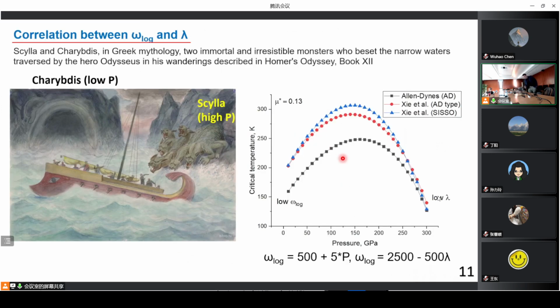So this negative correlation leads to a situation like the one described in classical Greek mythology, in the book about the travels of Odysseus. The ancient hero, in one of the episodes of this book, had to pass between two monsters: Charybdis, which is low pressure, and Scylla, which is high pressure. So when we use these two empirical correlations, for logarithmic frequency and for the correlation between logarithmic frequency and lambda, we can get such parabolic plots.